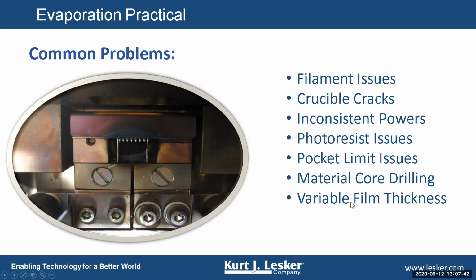So if I set my quartz crystal monitor for, say, 200 nanometers, and I run a film and I get 200 nanometers the first time, successive runs, I might get a little bit thicker and a little bit thicker and even a little bit thicker film. And generally that's an indication that the quartz crystal monitor is being shadowed either by the melt itself or another piece of equipment that's inside the chamber.